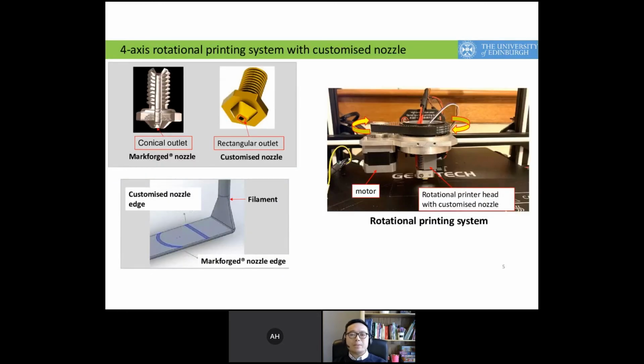We also developed a special nozzle with a rectangular outlet, in contrast to the conic outlet of the Markforged nozzle. As you can see from the sketch, the new nozzle gives a more uniform pressure distribution on the printed strip. To accommodate this special rectangular nozzle, we modified an FDM 3D printer and introduced an additional rotation when printing a curved path or turning around a corner. Basically, we use a motor to rotate the print head and make sure the nozzle outlet is always perpendicular to the print direction.